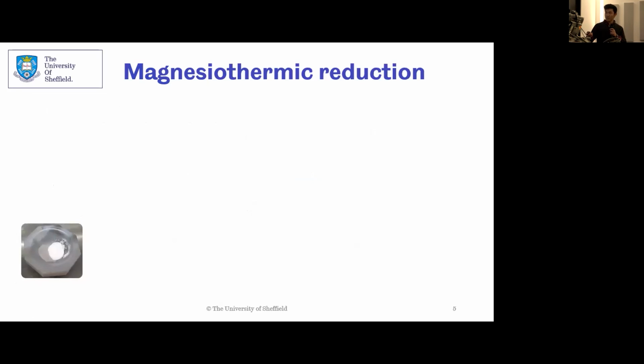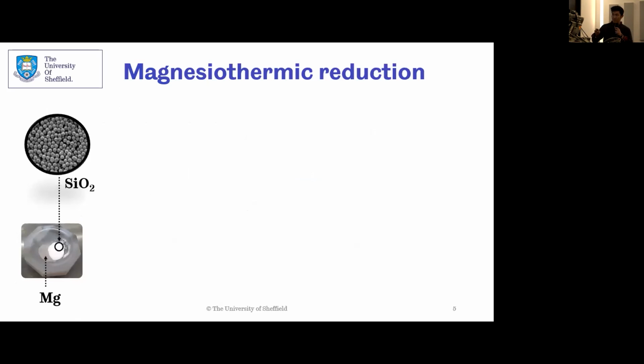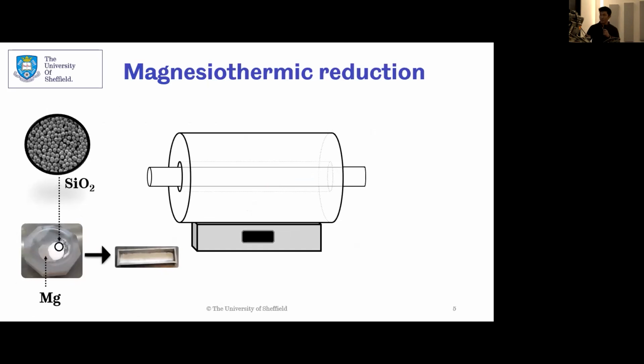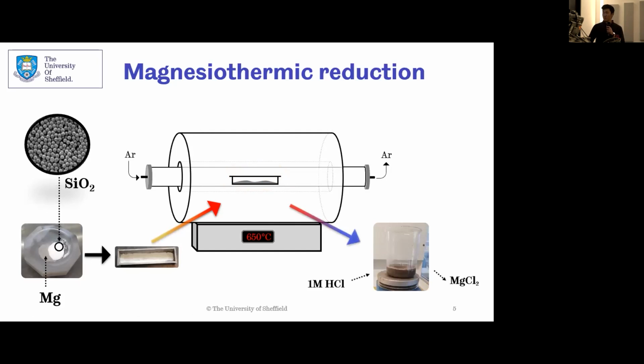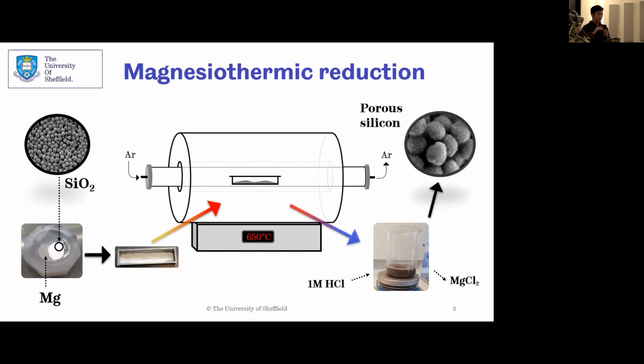So what does the method look like? Well, in a lab, the powders of silica and magnesium are ground and heated up in a furnace. But magnesium likes oxygen, and so there's oxygen around it in the atmosphere, so we have to seal the furnace and flow argon through it to make sure there's no oxygen in the system. This is then heated up to 650 degrees Celsius, 6 hours usually. Then put into 1 molar hydrochloric acid, which is really mild, and the magnesium chloride, which is in solution, is filtered off, leaving behind porous silicon. It's a cake, so it's actually a powder with moisture in it. This is dried in the drying oven and then put into a battery.